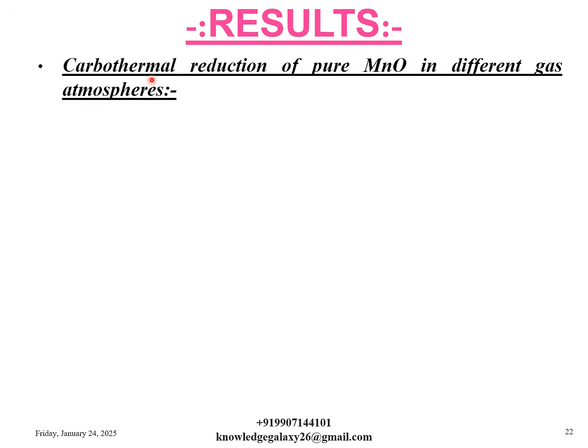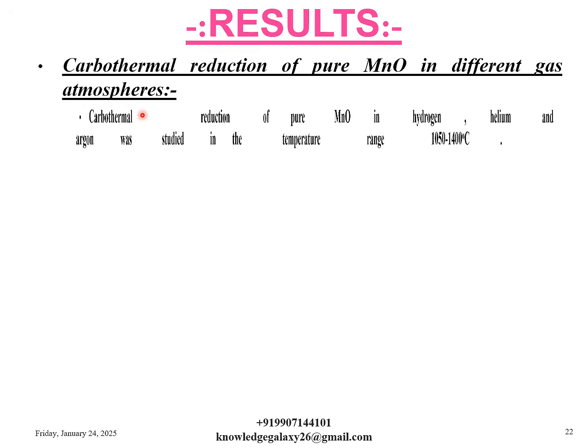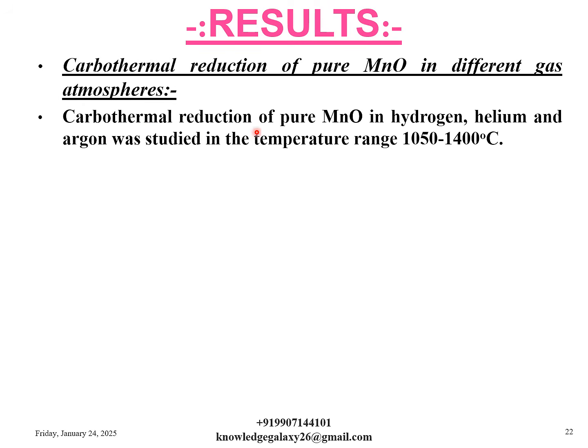Now I will discuss the results of the experiment. Carbothermal reduction of pure MnO in different gas atmospheres. This is the first subtopic of the results. Carbothermal reduction of pure MnO in hydrogen, helium and argon was studied in the temperature range of 1050 to 1400 degrees Celsius.